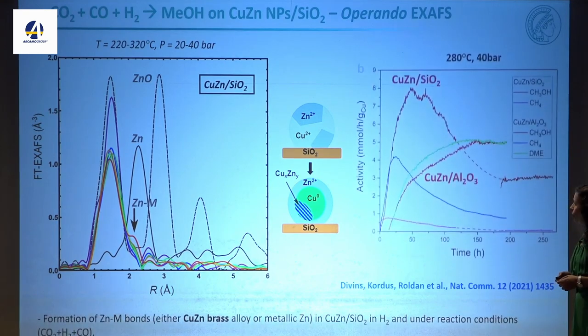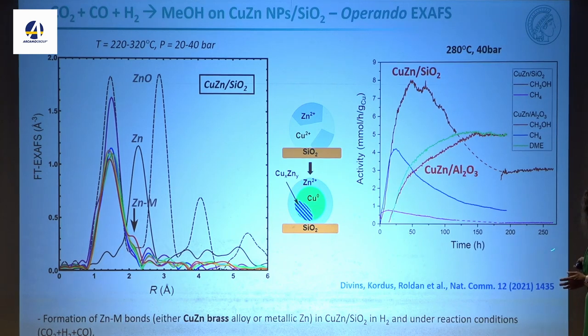And if you look at the performance of this catalyst over about, in this case, 250 hours, you can see that the copper zinc catalyst on silica that started to make the brass initially is very active, and then after about 50, 60 hours, when you start making a significant amount of brass, this starts to deactivate, and then it goes to this steady state. And when you have the same catalyst on alumina, where we didn't have the brass formation, where all the zinc became incorporated into the alumina, you see that the activity goes up, you activate your catalyst, and then it stays stable. The only difference is that on the alumina, you also make the dimethyl ether.